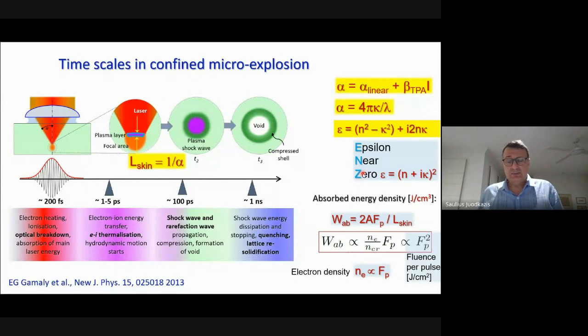The energy which we absorb can also be argued in terms of how we calculate it. But it's very useful to calculate energy in volume, because usually we are modifying a volume. If we are polymerizing, we are also delivering energy in volume and writing polymerized structures. So the energy in volume which is deposited will be simply the coefficient of absorption, the fluence which we are shining on that spot, and also where we absorb, so the skin depth. It's very easy to show, just from the basic rules of the Drude model, that those free electrons which we are exciting in the material are key to depositing energy.